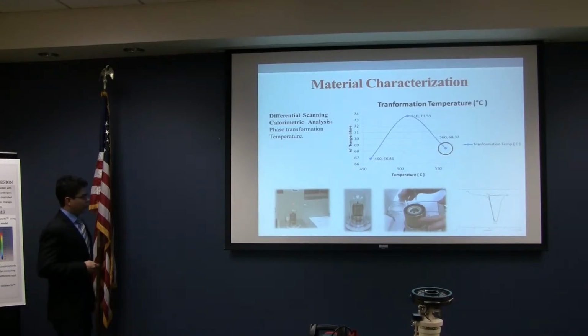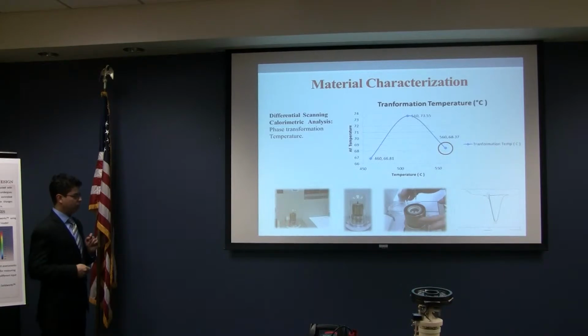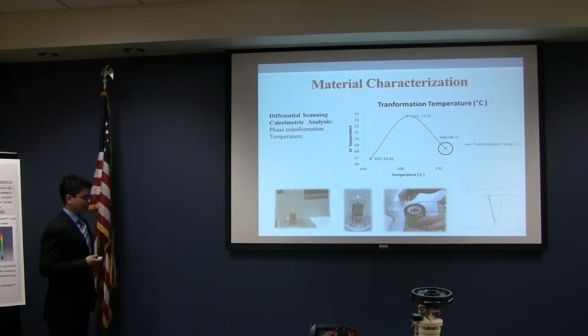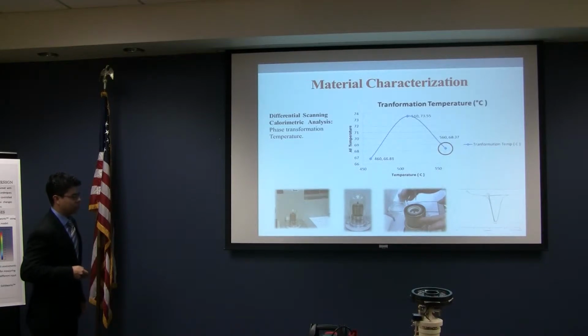What we do is we put a little piece of nitinol, which has been pre-treated, with 3 iterations. We treated the nitinol at 460 Celsius, 510 Celsius, and 560 Celsius. These are the different temperatures that we annealed the material at. After we annealed that, we took the samples and used the DSC machine and got the graphs. These graphs will tell us when the transformation occurs. On the x-axis, we have the temperature. So we are speaking about 60 Celsius, 65 Celsius.